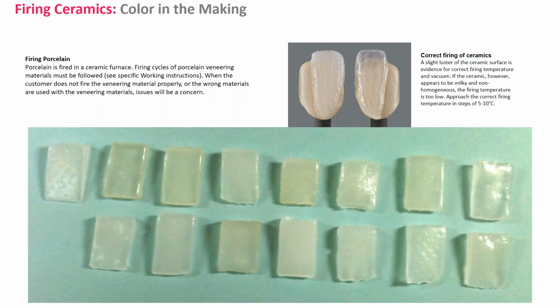What you don't want to see is something like this, where the clear comes out yellowish or brownish or is very opaque. This is a way that we can determine that your furnace is tuned up, in a sense. If you have contamination, you have to properly decontaminate your furnace. We usually fire our furnaces at 1,000 degrees Celsius and hold it for 15 minutes, and that pretty much burns out everything. If you are using multiple restorations in one furnace, PFM work, stuff with silver, stuff with gold, and then doing your all ceramics, especially when you switch over to all ceramics, make sure that you do yourself a favor. Clean your furnace periodically. You may have to do it every week, right?